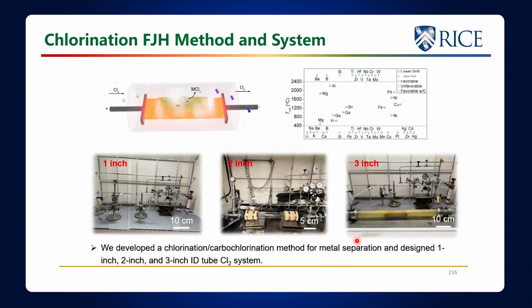And so we built a system that has a carbon layer between two electrodes. You put your material here that you want to separate, you flow in chlorine. It's going to give out oxygen as the metal oxide converts to the metal chloride, and the metal chloride would evaporate. What you can do is look at the temperature at which these metals would react and begin to look at it in this way.